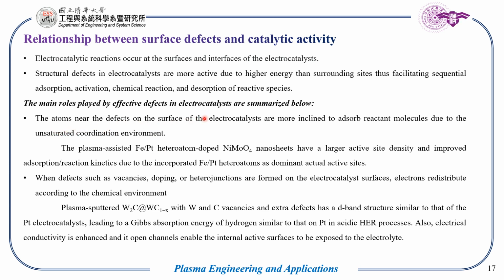effective defects of the electrocatalyst can be summarized below, and here we can see the atoms that are nearer to the surface of the electrocatalyst will be more available for the reaction. This can be seen in the case where Fe and Pt heteroatoms were doped in NiMoO4 nanosheets, where the Fe and Pt heteroatoms have dominant active sites in the nearer region, and they act as a source of adsorption, and different reaction kinetics occur in those areas.